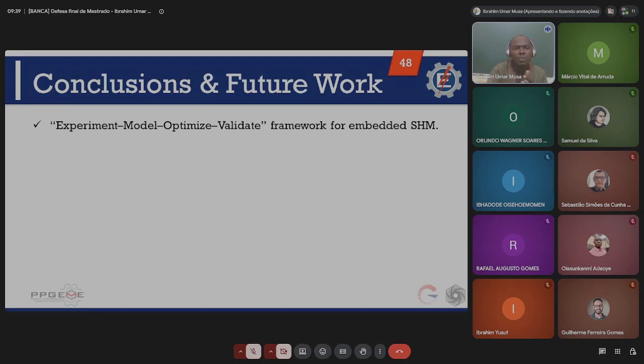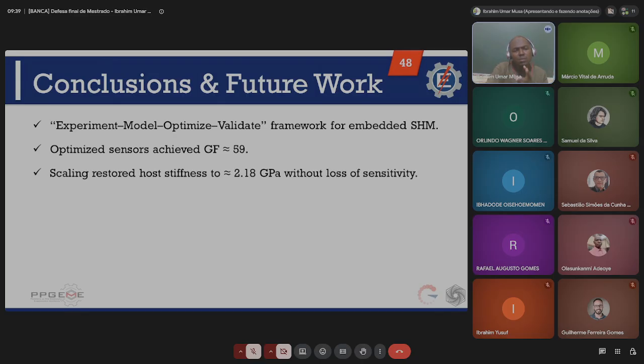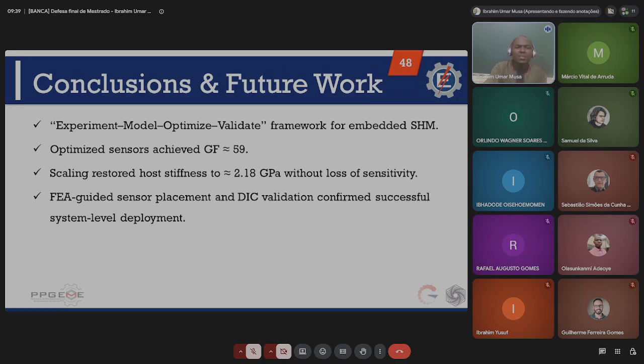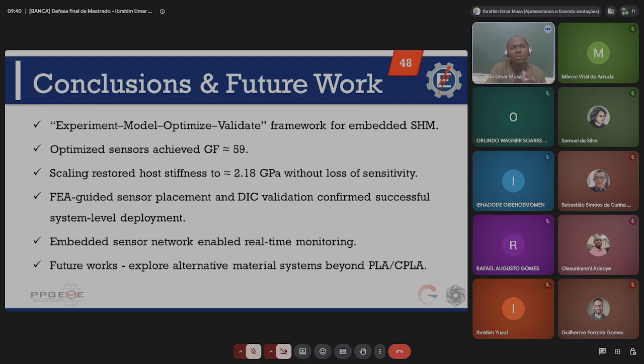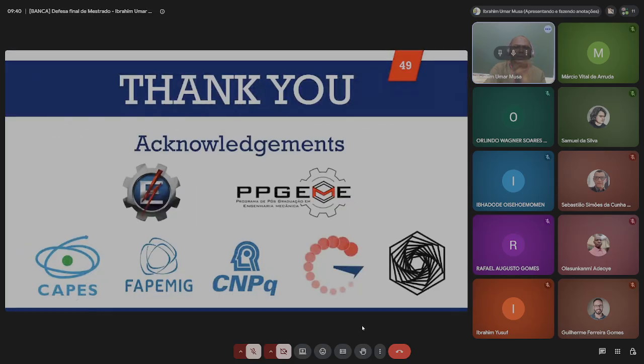And in conclusion, we were able to prove that the experimentally validated optimized framework was successfully implemented, and that the optimized geometry gave a gauge factor of 59, and the scaling restored back the host stiffness without sensitivity compromise. And the finite element guided sensor placement also confirms successful system level deployment. The embedded sensor network also enabled real-time monitoring. And finally, future work should explore alternative material systems beyond just PLA, such as CPLA.